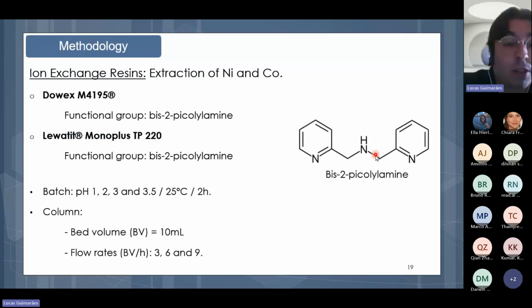So we also studied another purification technique called ion exchange resins. We used two different resins with commercial names, Dowex and Lewatit TP220, in order to try to absorb and extract nickel and cobalt from the solution. They both have this functional group, bis-2-picolylamine, represented here. And according to literature, it is a very good and selective functional group for extraction of nickel and cobalt. That's why it was used. Batch experiments and column experiments have been done for this technique, with different parameters analyzed as well.